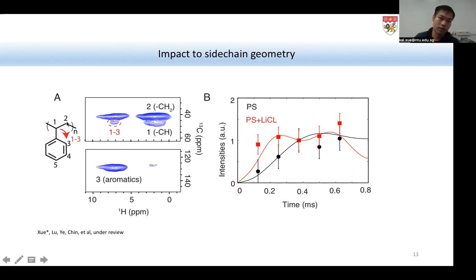Since this is a very complicated system, with polymer structures stochastically stacking and entangling, what we observe here is only an averaged signal. So I would not interpret this RFDR curve directly into a distance. But what we can definitely see here is that with the addition of lithium chloride, the structure or the dynamics of this polystyrene has changed.